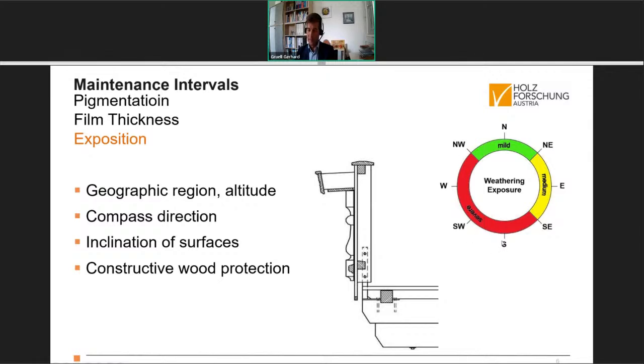South direction has also the highest irradiation from sunlight. In the east, it's usually medium conditions, medium weathering exposure, because the main weather direction is very seldom from the east side. There is some sun exposure, of course, but the driving rain and moisture conditions are not so severe on the east part. And there are mild conditions in the north facing areas, because the weather direction is very seldom directly from north, and the sunlight is not so much on the surfaces. But on the other hand, the north surfaces have a greater tendency to wet conditions, and that's why sometimes you find more algae and fungal growth on the north surfaces of a building.